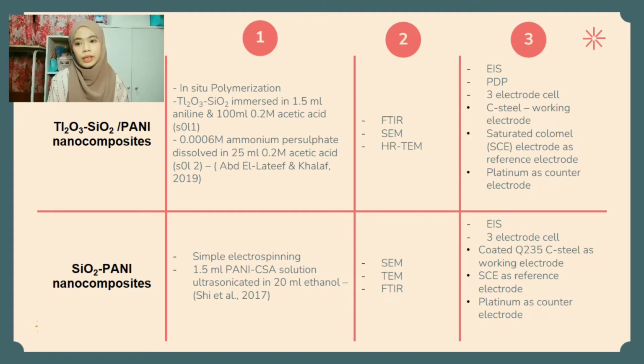Solution 2 was created by dissolving 0.0006 molar ammonium persulfate in 25 ml of 0.2 molar acetic acid. Then, at room temperature, solution 2 was added dropwise to solution 1 and swirled for 12 hours. Silicon dioxide polyaniline nanocomposite was prepared by a simple electrospinning strategy. In 20 ml of ethanol, 1.5 ml of camphor sulfonic acid doped polyaniline (PANI-CSA) solution was ultrasonicated.